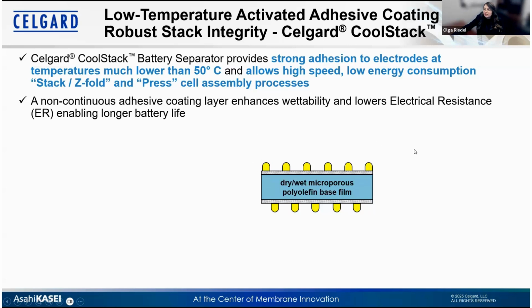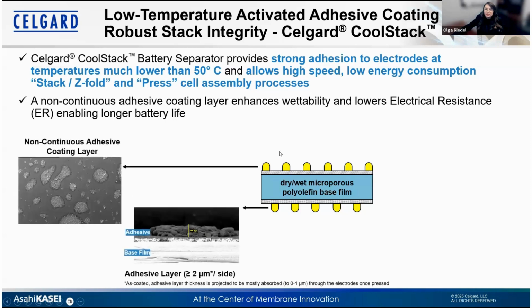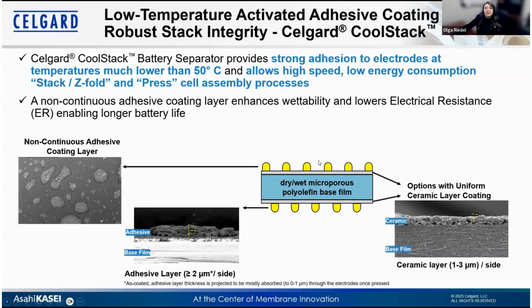Here you can see a schematic structure of our separator. The non-continuous coating creates anchor points with the electrodes to stay in place while preserving porosity, air permeability, and also the ion transport. The adhesive layer is usually about 2 micrometers thick per side, but once you press the separator, it's largely absorbed by the electrodes. We can also combine our CoolStack adhesive coatings with ceramic coatings, which range typically somewhere between 1 and 3 micrometers, depending on your requirements.